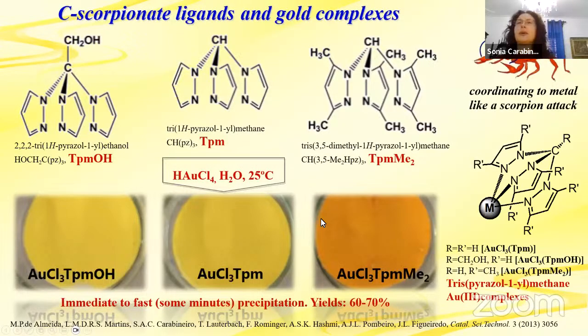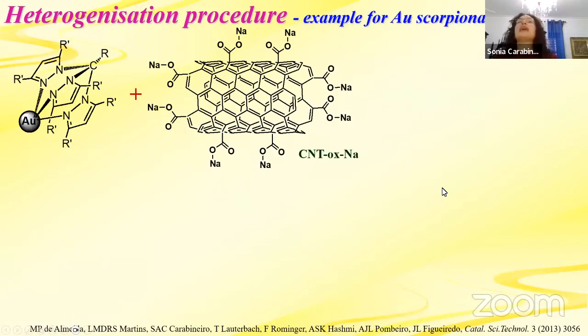70% yield. So we obtain these gold scorpionate complexes that we are going to use. And here we have an example for the gold scorpionates and their heterogenization on these functionalized nanotubes. We did it on these functionalized nanotubes, also on the oxidized nanotubes and on the normal nanotubes, and on other carbon materials as well, functionalized or not. So a lot of samples were tested.